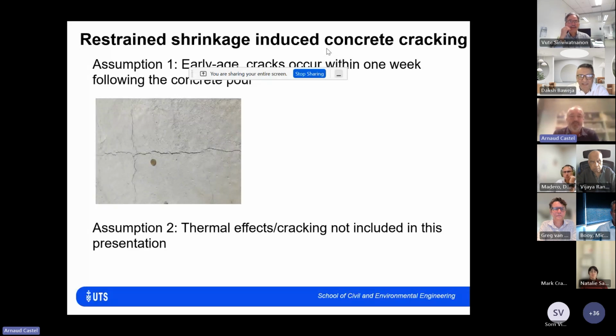Those cracks are really bad cracks. They're not planned, and there's no way basically to control the crack width. And we know that corrosion of reinforcement in cracked concrete is based on the assumption that we keep the crack width small. Then self-healing of concrete is there to basically prevent corrosion from happening. So if you have wide cracks, that doesn't work. So those are really bad.